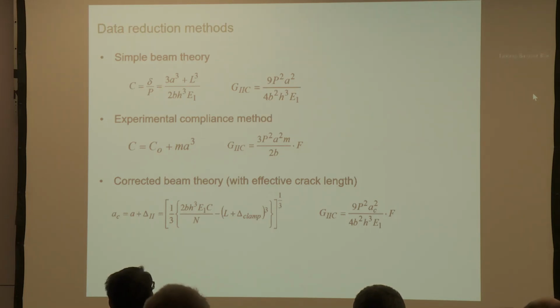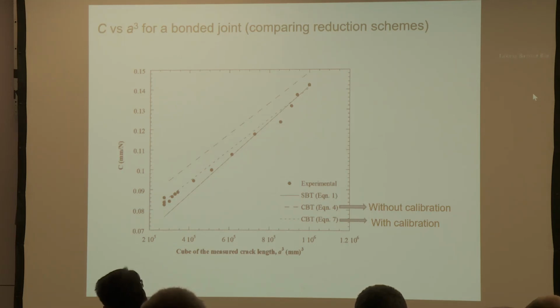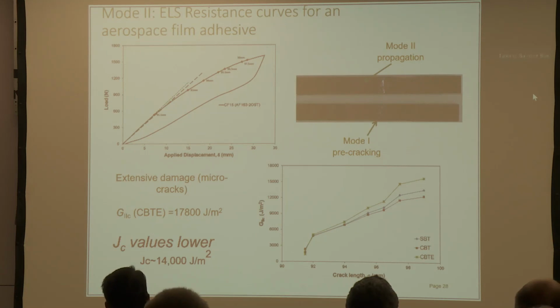So, of course, one can go through a similar sort of procedure. One can apply simple beam theory and experimental compliance methods. One can develop effective crack length approaches. So all of these things can be done a little bit analogous to the Mode 1, and one can look at how they improve the compliance to the crack length variability, the relation. And one thing we can see here is that because we have a clamp in the experiment, we do have to calibrate that clamp out. But indeed, we can get a theoretical compliance which looks pretty close to the experimentally measured one. But what I would say about this is the method, and certainly the G analysis with effective crack length approach, I think has passed the limits of its validity.